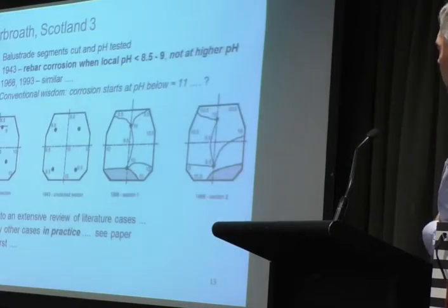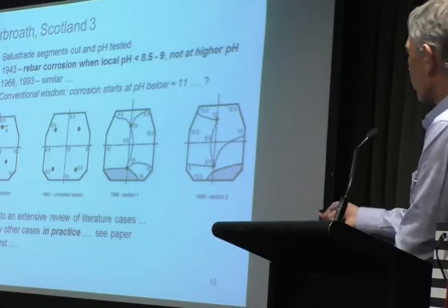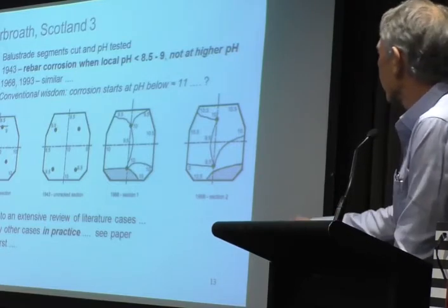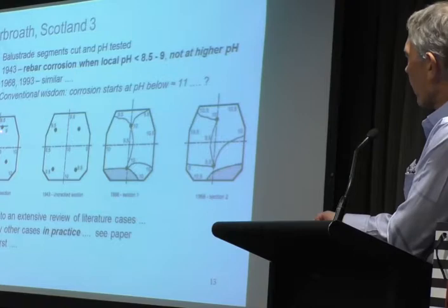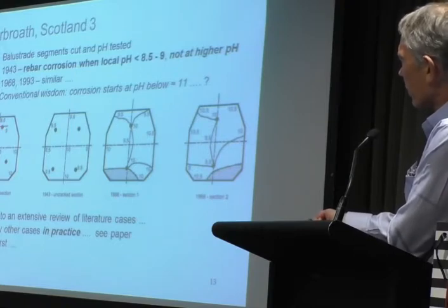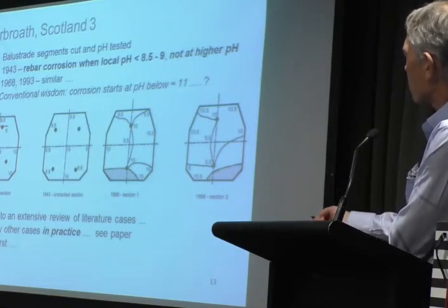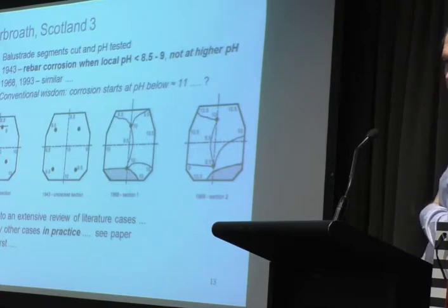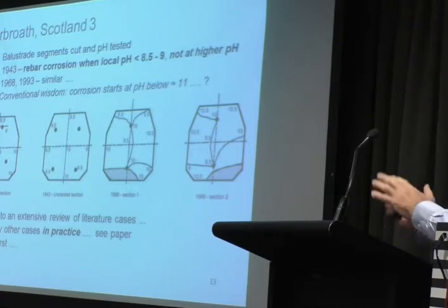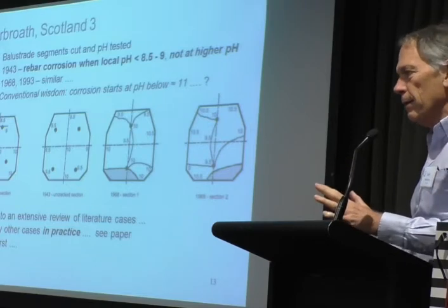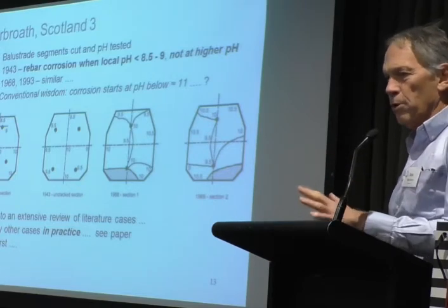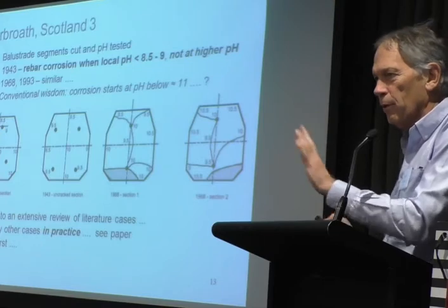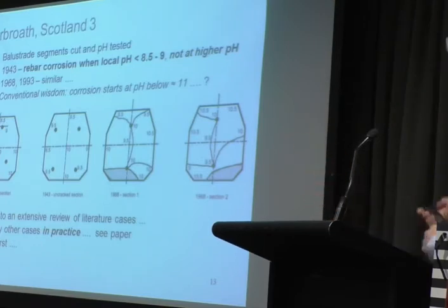So we looked more closely at these samples. These are just some random samples. 1943 concretes on this side. And if you look at the pHs, you'll find this cracking and therefore reinforcement corrosion only when the pH is around 8.5 to 9. The bars that are in higher pH concrete, there's no evidence that we could see of reinforcement corrosion. There may have been some microscopic amount of corrosion, but let's not worry, nothing to cause any problems.